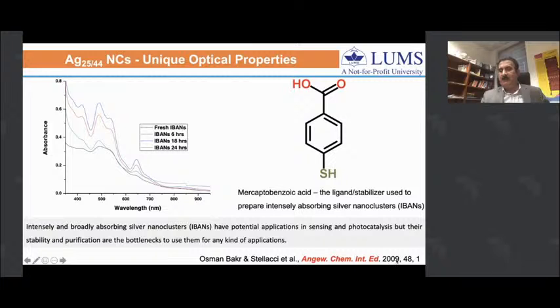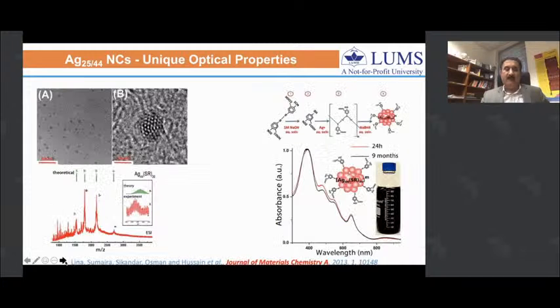Luckily, I was visiting his group during the same period, sometime in 2010. I came across this problem, and when I came back to LUMS, we started exploring how we could improve the stability of these silver nanocrystals. For that purpose, we used ligands which, in addition to the carboxylic group, also have a nitro group. Basically, it was our finding that if you increase the hydrophilicity of these nanoclusters, they will be more soluble in water, in aqueous media, and they will be more stable as well.